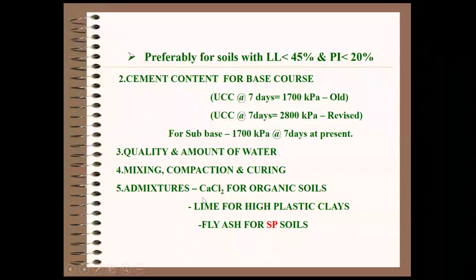Okay. So initially some 3 to 4% lime if we add to the black cotton soil, most of its plasticity properties can be overcome, and later if you go for the cement stabilization, then you can reduce the cement content. That is the purpose here. If organic content is present, 2% calcium chloride can modify the soil property, and poorly graded sand is to be modified or amended by the cement stabilization instead of using only cement. You can supplement fly ash so that it will be economical. That is what the admixtures mean along with the cement stabilization.